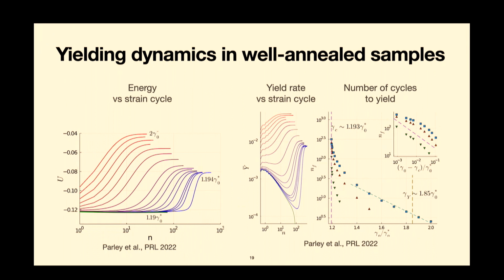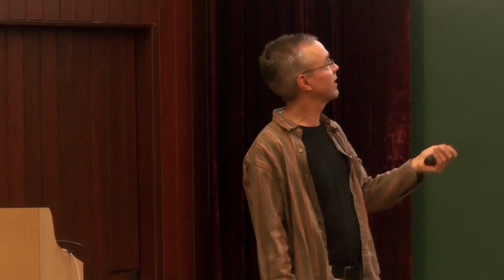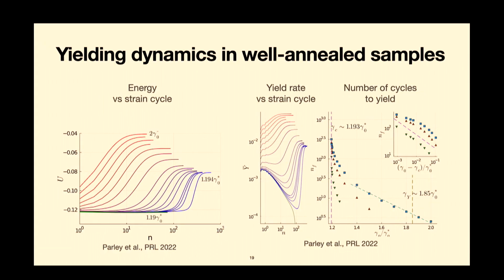We can quantify that by asking, how many cycles does it take before the system actually fluidizes? We can measure that in various ways. Let's focus for now on these blue squares here. We defined that by saying, when do we reach 75% of the final fluidized yield rate? That's basically somewhere near here. At this point we say the sample has reached fluidity, it's been fluidized. And what I'm plotting here is how this quantity varies with strain amplitude.